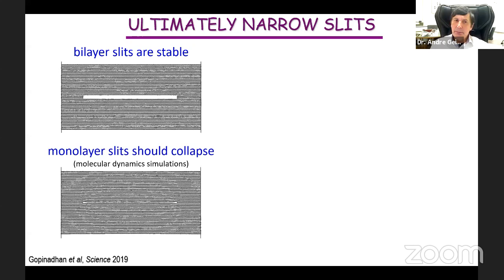We improved on this research quite recently by making even smaller slits. I described to you by taking two layers of graphite in those capillaries on the previous slides. And our molecular dynamics simulation shows that it should collapse. Whatever we tried in molecular dynamics simulation, when we try to extract only one atomic plane, capillaries collapsed. We tried to improve really, really hard, but capillaries always collapse.